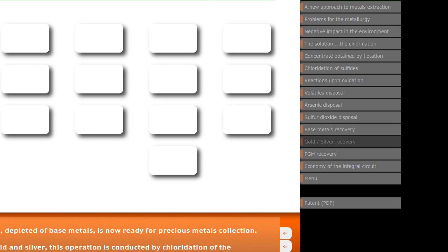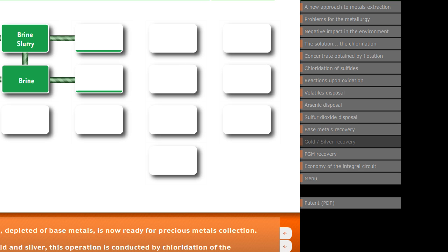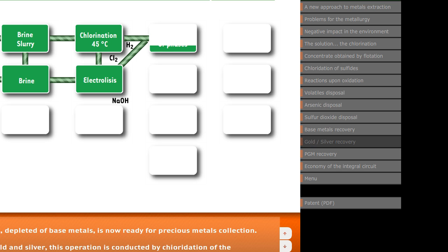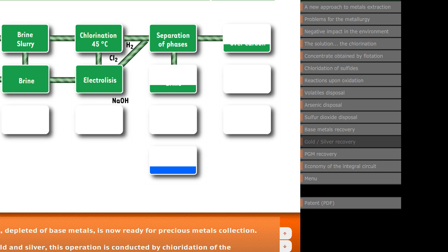Oxidized ore, depleted of base metals, is now ready for precious metals collection. In the case of gold and silver, this operation is conducted by chloridation of the substrate with added salt, 5% by weight, with elemental chlorine at about 45 degrees Celsius. This chlorine is doped with traces of bromine in order to benefit from the great reactivity of this element towards gold. The gold bromide thus first formed is then transformed into a gold chloride due to the greater oxidizing potential of chlorine. This is accompanied by the regeneration of the catalytic amount of bromine.